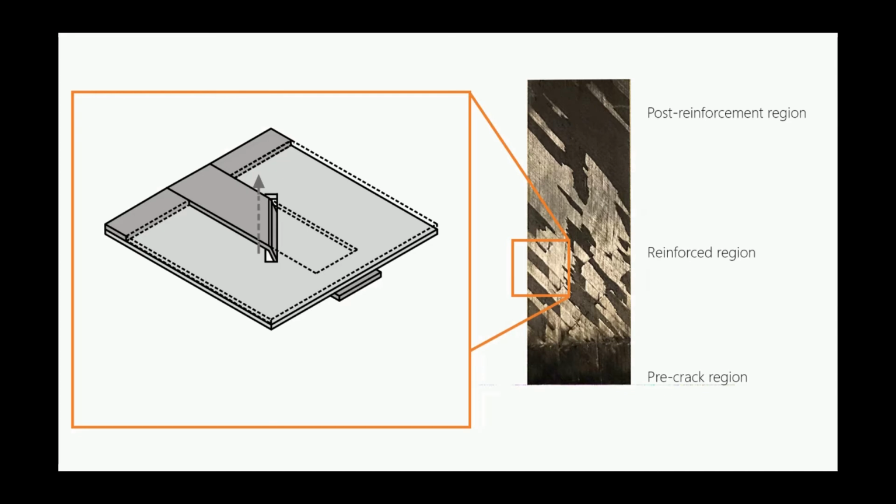However, from the fracture surface it is apparent that the delamination instead jumped over the tab, as follows. Therefore, in the actual experiments, the tab did not remain attached on both sides of the delamination and therefore could not act as a bridge.